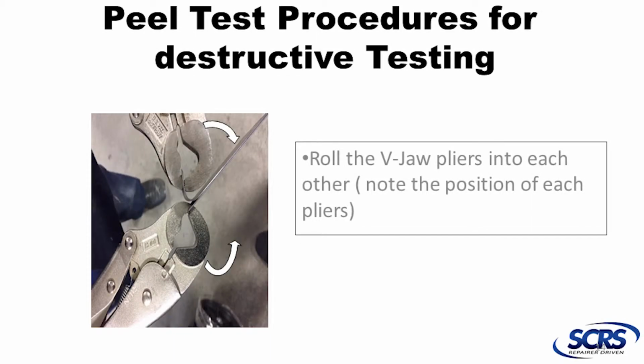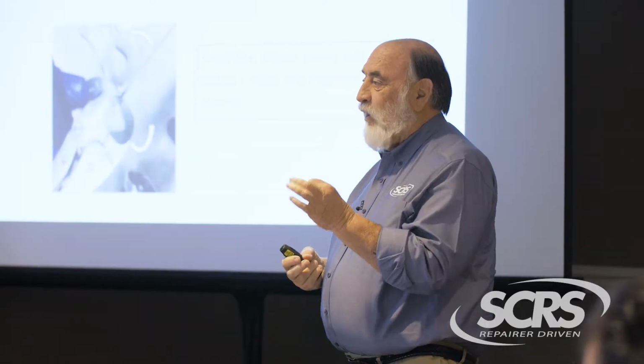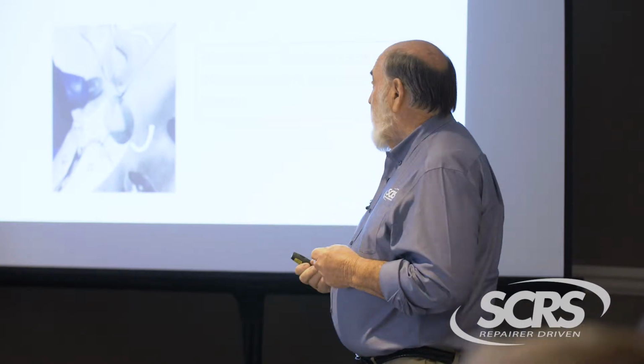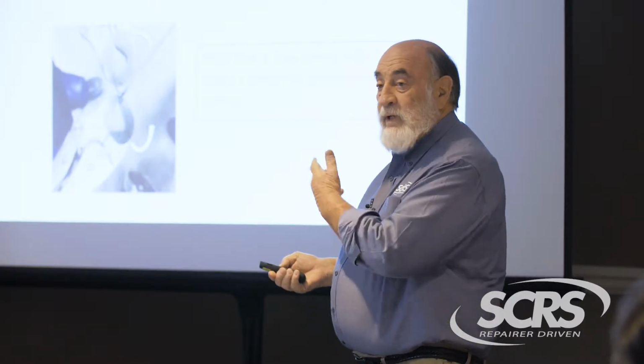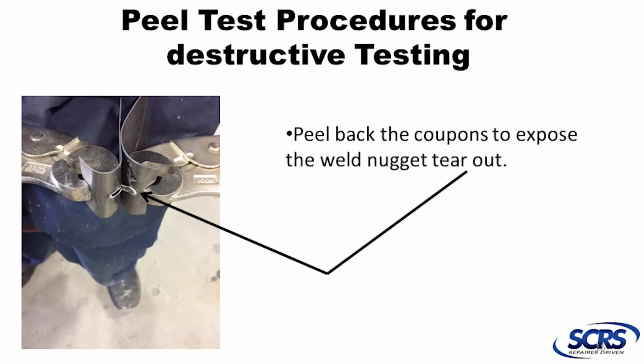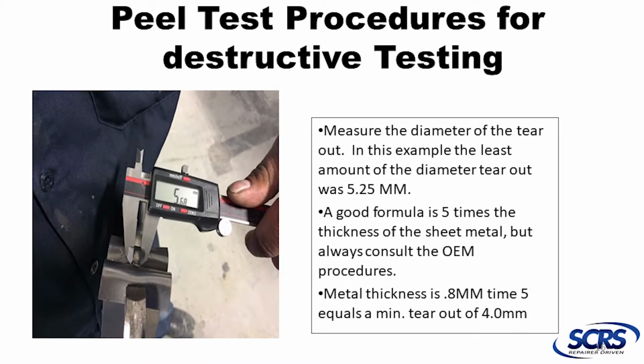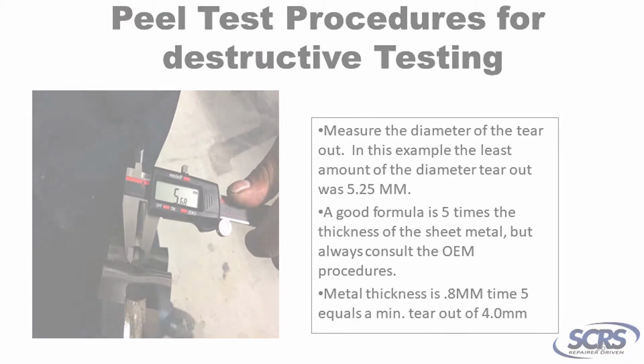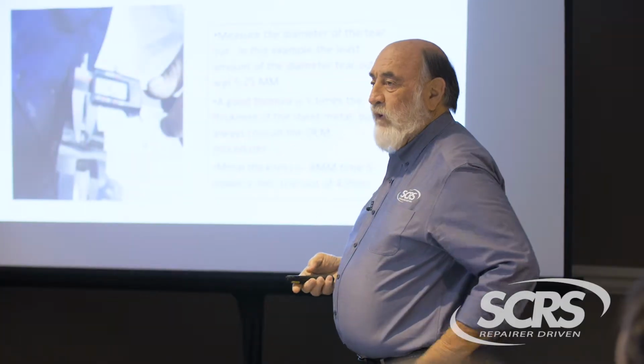Now these pliers are what are called V-jaws. What they were designed for is to put these pliers around a bolt to loosen it up and hold it. Well, what I did is I put them so that the round edges go in and you can peel the coupons apart right in your stall. I've done up to 1.4 millimeters thickness on each panel and broke them apart. So this can be done right in the stall. You don't have to have a vise. You can see here was my tear out. And then we measured it. When I took an average of the whole size, it was a little over, 5.25 millimeters.